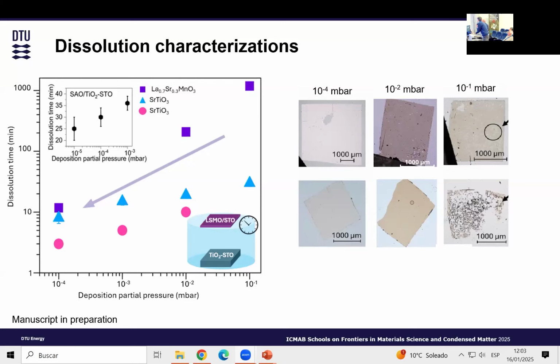The way that we're preparing it is by normal solid state reaction. So it's nothing special about it. I don't know if I have to go into much detail, but it's solid state reaction that we do, and then the pressing. We also approached other companies and tried to buy from them just to compare, because at least our experience is that not everything is the same. You can buy a target from one company and from another one, and you put them together and you see that the dissolution time or the release time is not the same. It's the same with the crystals that we buy. We can buy one crystal from one company and another crystal from another, and you find that the crystals are not exactly the same. So all of these problems exist. I'm not underestimating them. They are there on top of all the other challenges that we have.